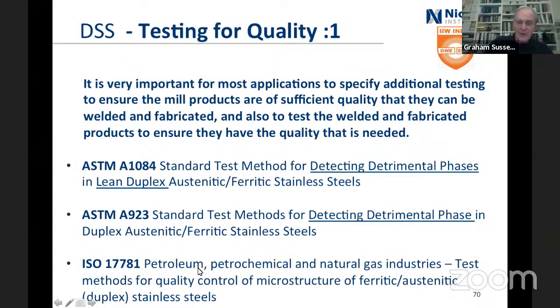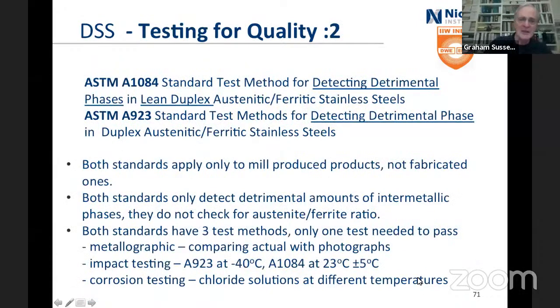All of them have been wrapped up in this ISO standard, which tests quality control of the microstructure, which is what those two do. And also it looks at the ferritic austenitic duplex balance. These don't. These apply only to mill-produced products, not fabricated. They only detect the intermetallic phases. They don't check for the ferrite-austenite ratio. You're meant to do it separately.